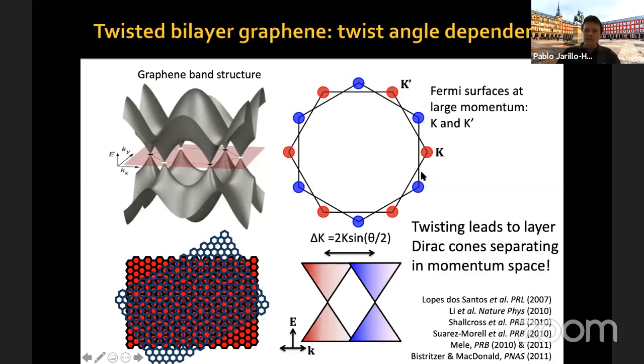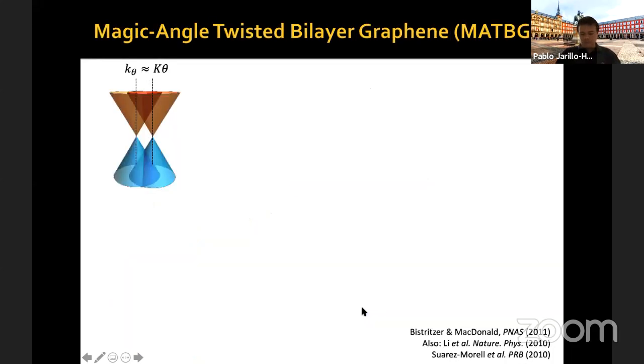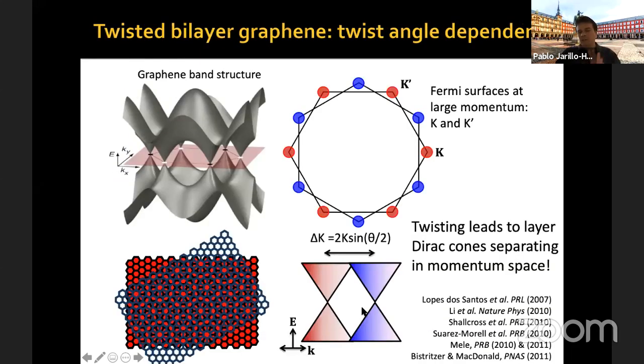As you can see, this leads to the Dirac cones of graphene layer one and graphene layer two separating in momentum space. So twisting leads to the Dirac cones separating in momentum space, and the amount of separation depends on the angle of rotation. Let me start from a small angle of rotation, so that the separation in momentum space between these Dirac cones, between these charge neutrality points, is proportional to the angle.